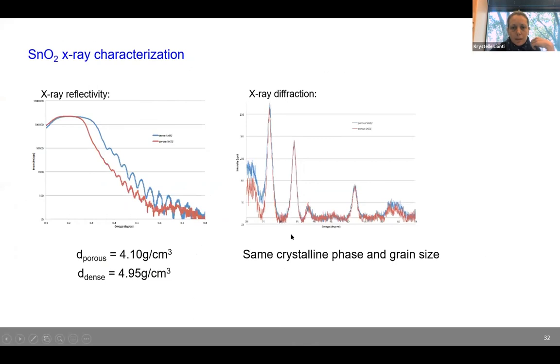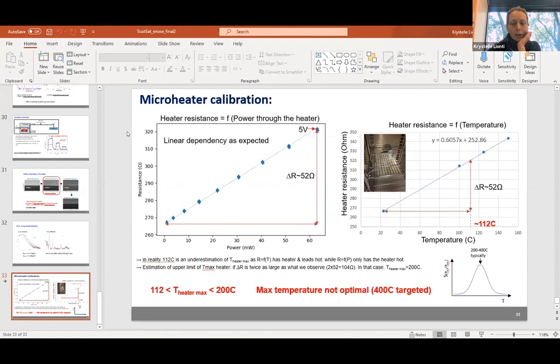So we took a couple of electrical measurements. The first one was measuring the resistance of the heater as a function of the power that went through it. We can only apply up to 5 volts, so we looked at the delta in resistance between 0 and 5 volts, and it's about 52 ohms. The second measurement was to place the whole MOS microheating platform inside a high precision oven, and we monitored the heater resistance as a function of temperature. We couldn't go too high in temperature, but thankfully the response is very linear.